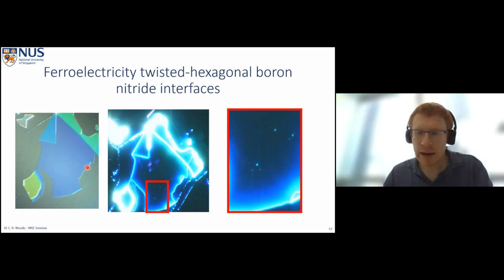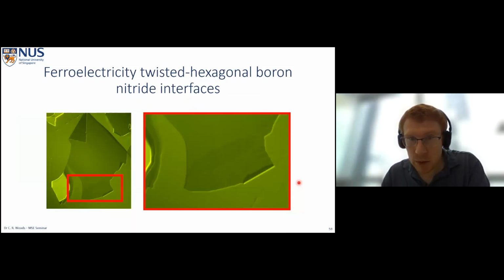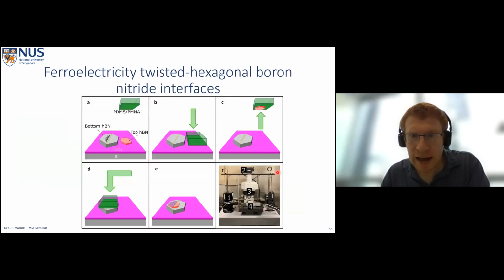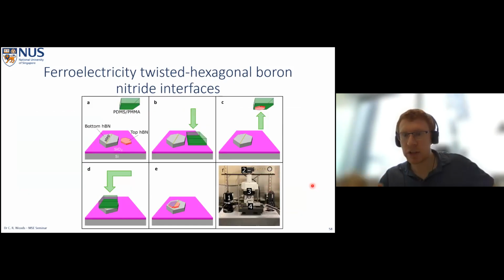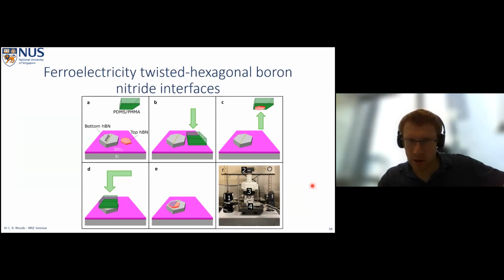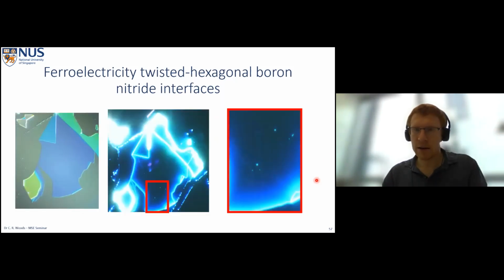orientation. In terms of getting precise alignment, i.e. the difference between 0.1 degree, 0.2 degrees, it's a bit of a random process. I'm afraid our mechanical transfer stage has a rotation, but we're really only getting alignment which is plus or minus at best half a degree or something like that. And we're just hoping that we get it right. Maybe it has a slightly better angular resolution than that, but we can't do it perfectly. So we can only get, say, plus or minus 0.5 degrees in our samples.